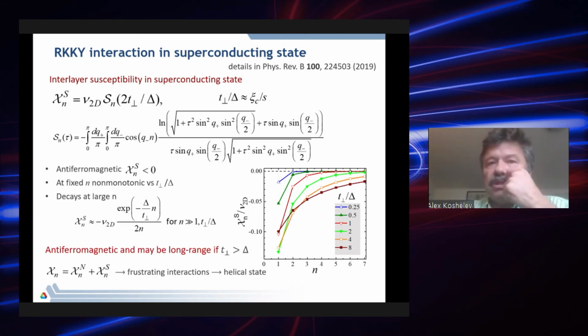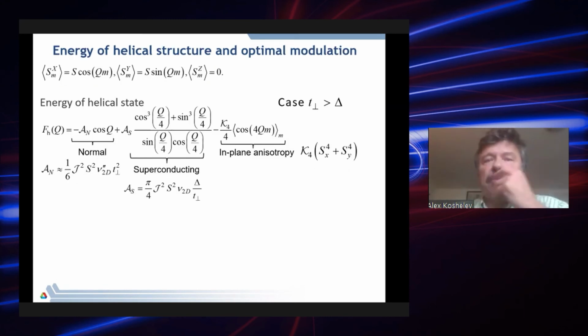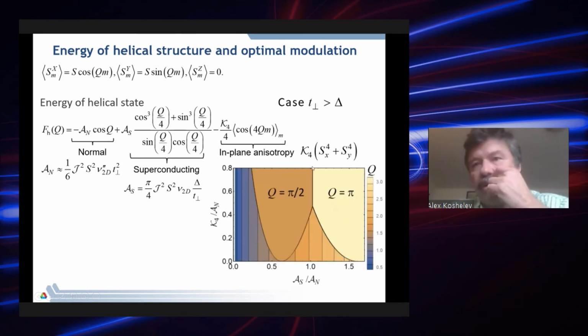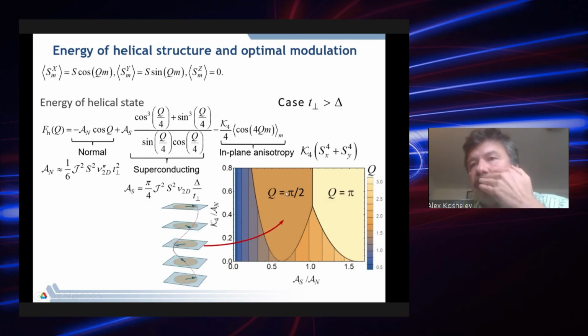So we have two contributions. The normal part is ferromagnetic and short range, and the superconducting part is antiferromagnetic and long range, and this creates frustration, which may lead to a helical state. To demonstrate, I performed a simple illustrative calculation. I considered these two contributions. In the case when the hopping integral is bigger than the gap, this gives these two contributions to the energy as a function of modulation vector. I also added anisotropy, which fixes the orientation of the helix in the lattice. This model gives the following phase diagram in the parameter space. The basic message is that in a certain parameter range we may have a modulation vector equal to half pi, which is realized in RbEuFe4As4, the 1144 compound.